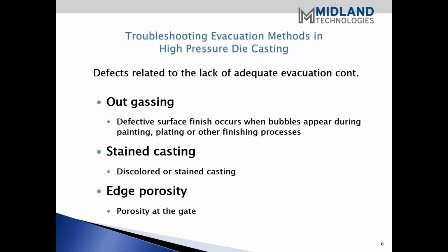It continues to outgas if you don't use some means of minimizing that gas after or during your injection of the metal, or it can also be addressed at a later time. I've had this experience many times with castings, where you would heat the casting up, and the outgassing would occur on the surface of the casting, ruining either paint or plating. One way that can be addressed is to post-heat the casting to precipitate the outgassing of the part prior to finishing. There are certain temperatures and lengths of time associated with the various alloys to facilitate that outgassing.